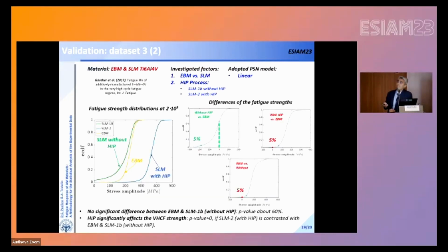And as you can see, by analyzing the fatigue strength distribution at 2 times 10 to the 9, the very high cycle fatigue region, we have that the HIP process significantly increases the fatigue strength with respect also to the EBM process. Then by comparing the fatigue strength for all the data sets, we got the statistically significant effect of the HIP process with respect to the EBM or the SLM without HIP process.